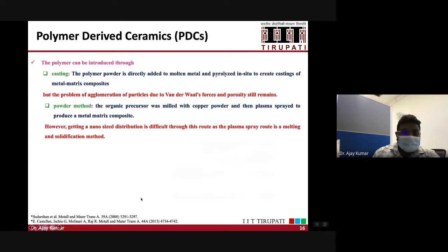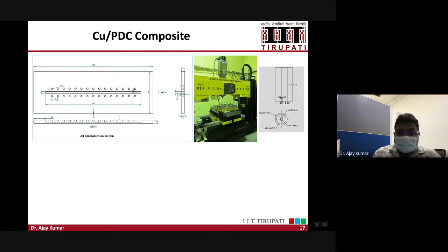Now, there is work reported on using these PDCs in casting as well as powder. When people tried to use these PDC materials in the casting process, they found agglomeration of the particles due to van der Waals forces, and porosities. And when they used the powder metallurgy process, they did not get the nano size distribution. That is why we have used the friction stir processing method.